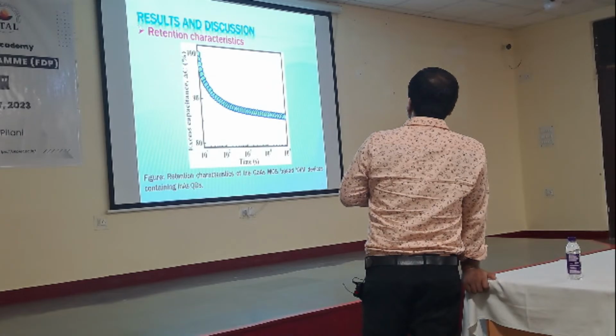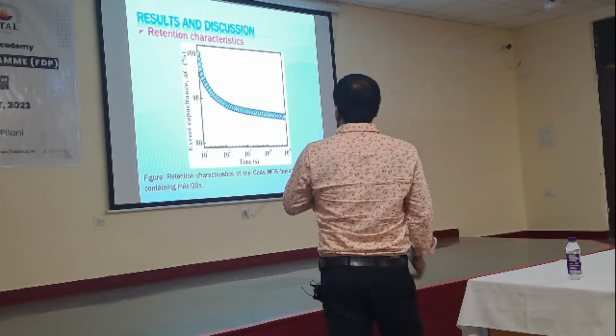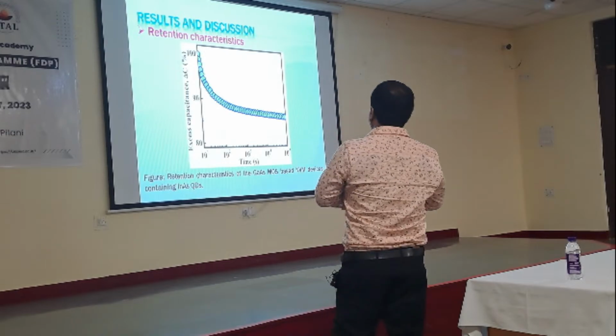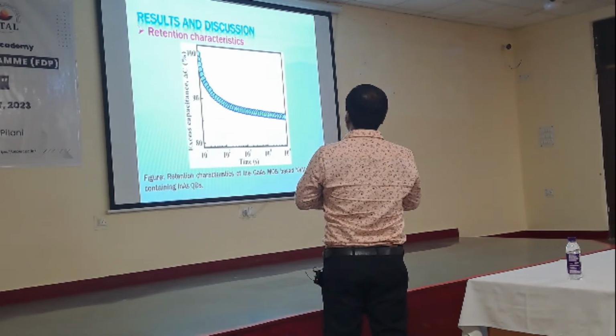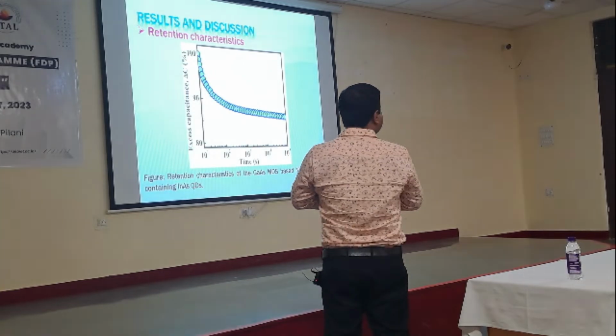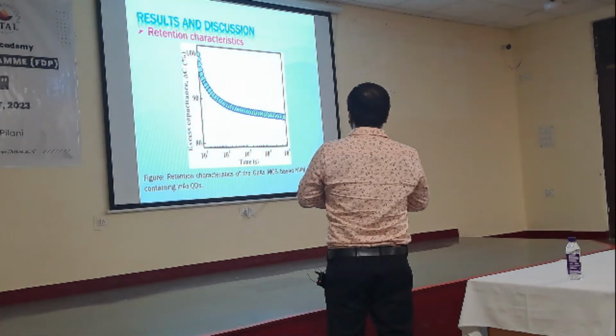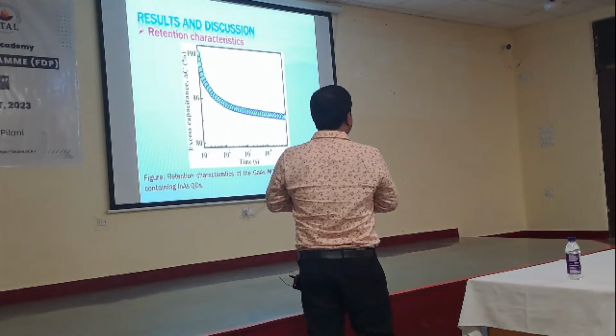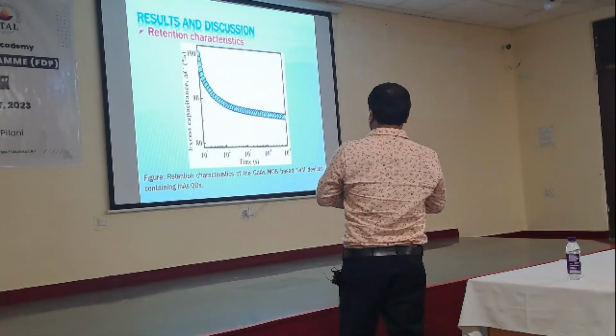Now this is the charge retention capacitance. You see up to 10 to the power 5 seconds, you can store the charges at least 87.1 percent. So your device retains charge for 10 to the power 5 seconds, which is almost more than 24 hours.